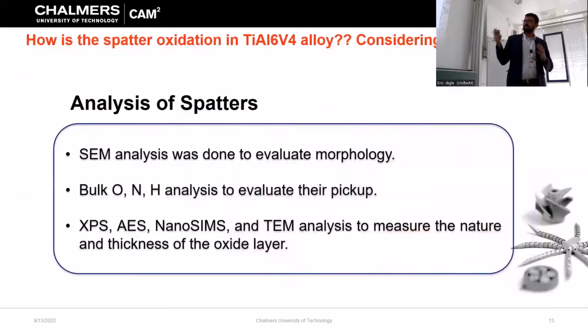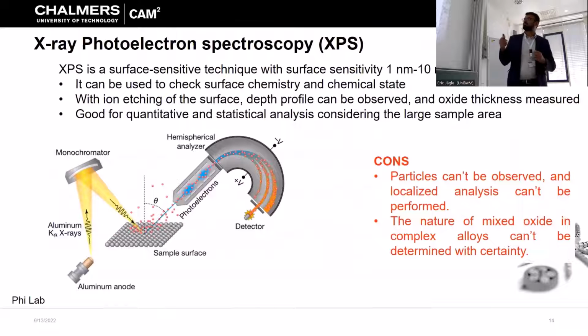We did SEM analysis, then bulk oxygen, nitrogen, and hydrogen analysis. Then we did a very comprehensive XPS, AES, NanoSIMS, and TEM analysis to analyze the thickness and nature of the oxide layer. For people who don't know about XPS, it is a very surface-sensitive technique where we can measure the chemistry and also the chemical state in the range of 1 to 10 nanometers. With ion etching, we can also do chemical profiling with depth, and it is good for quantitative and statistical analysis. But there are some cons: we cannot see the particle itself, so we cannot do a very localized analysis. And when a complex alloy comes into play, differentiating between different mixed natures of oxide gets complicated at times.